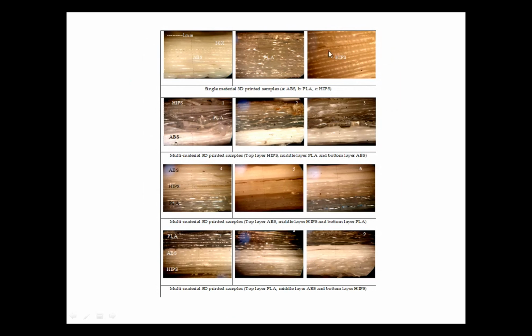Now you see here, in this particular case, in case number 1, case number 2 and case number 3, I have the lowest layer of ABS over which the PLA was there, and over that there was a HIPS. So you see the PLA is bulging out, right? So the material is coming out. That means if I have this type of layer combination, in which the lowest layer is ABS followed by the layer of PLA followed by the layer of HIPS, I may have a problem in the mechanical properties.